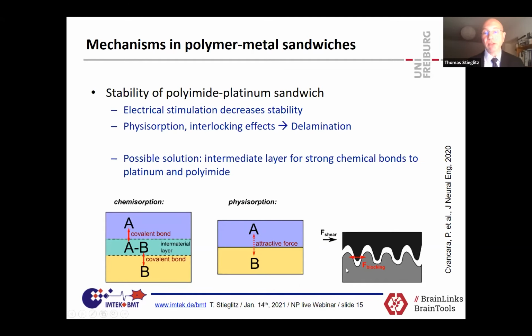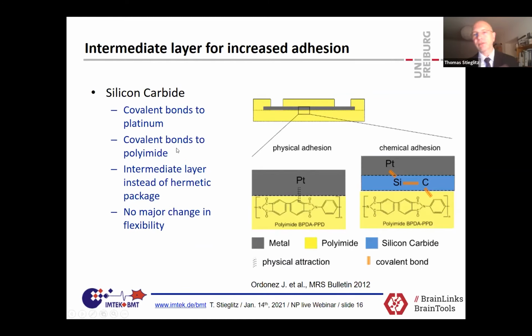What can you do? Well, normally you have more or less rough surface and you put things together, and they might somehow stick together because of that mechanical interlocking or some physisorptive processes. But to make it really stable, you need a strong bond with a lot of energy so that it sticks together. And that was our challenge. And we stole the idea from Stuart Cogan and modified it a little bit to use silicon carbide to provide chemical bonds between the metal, which is platinum in our case, and the polyimide, so that the carbon side anchors to the backbone of the organic side, and the silicon with platinum silicides anchors to the metal layer. This is the idea, and I show you some examples, or one example, how this looks like if it really sees a human being over 6 months.